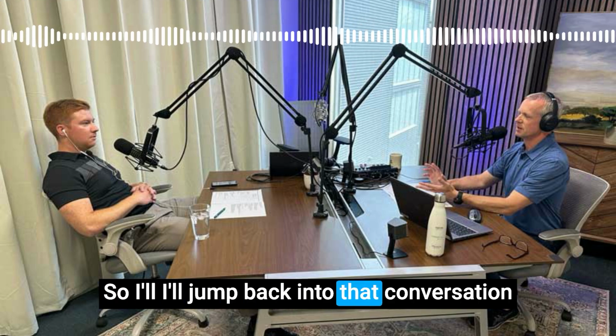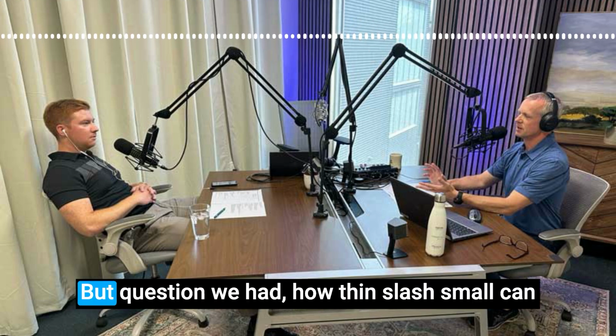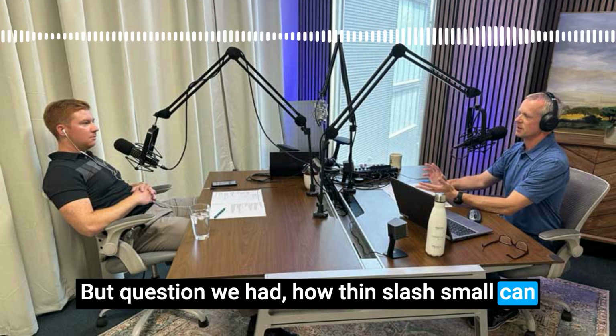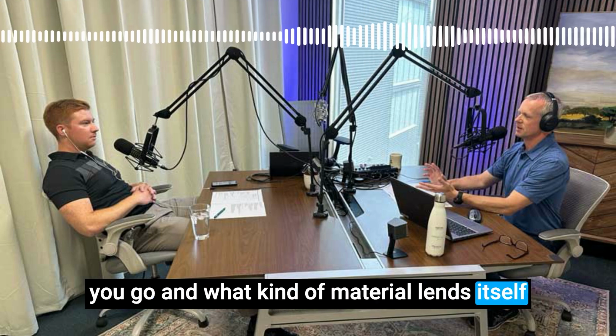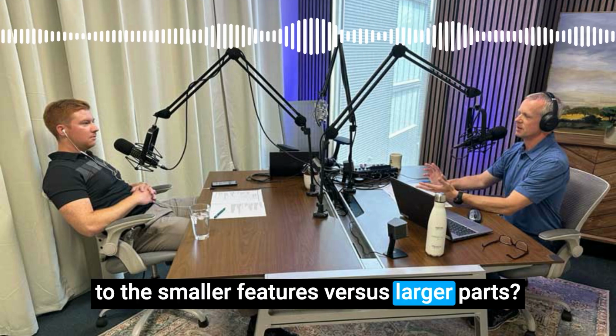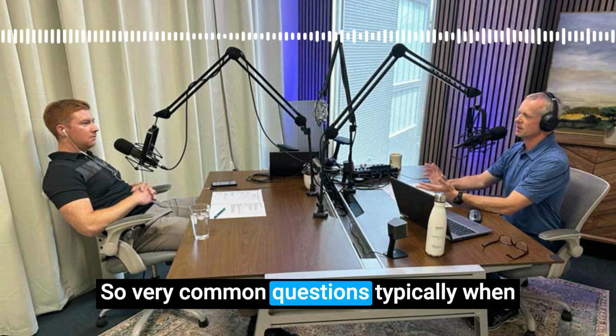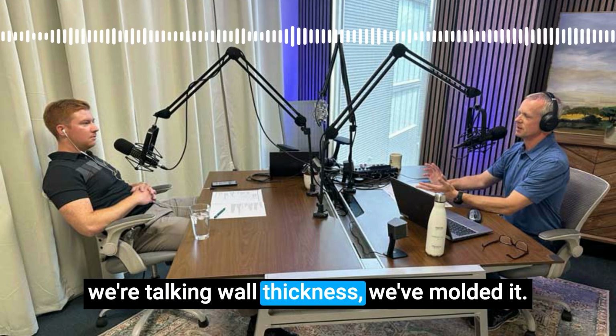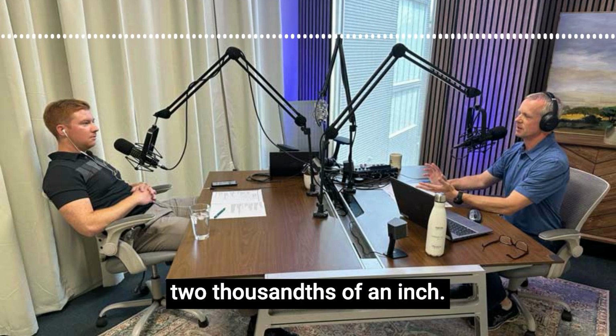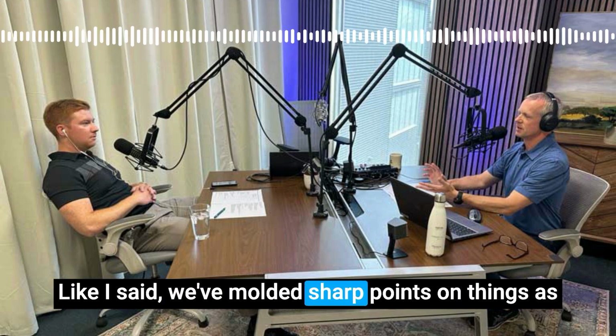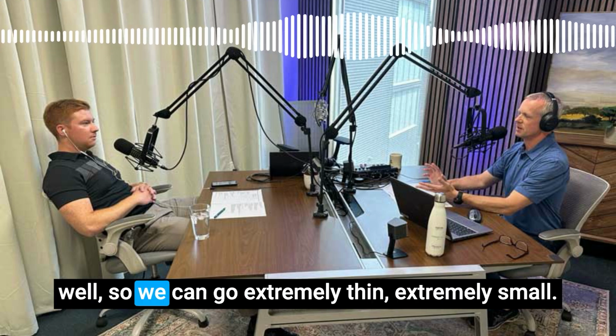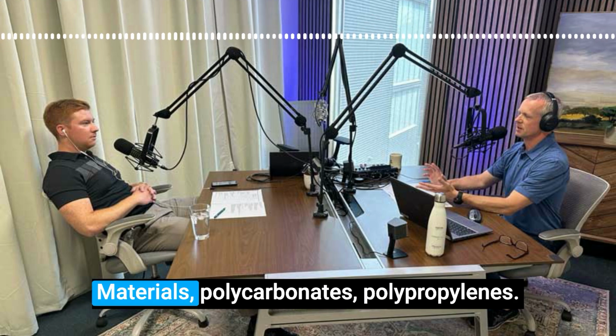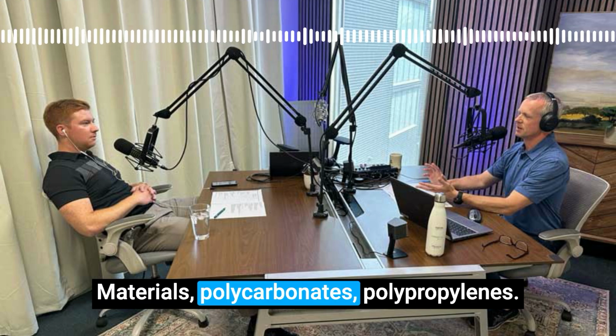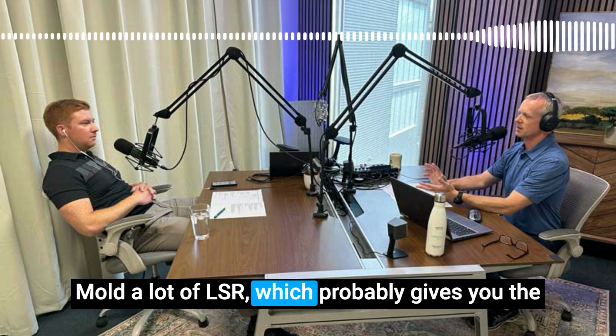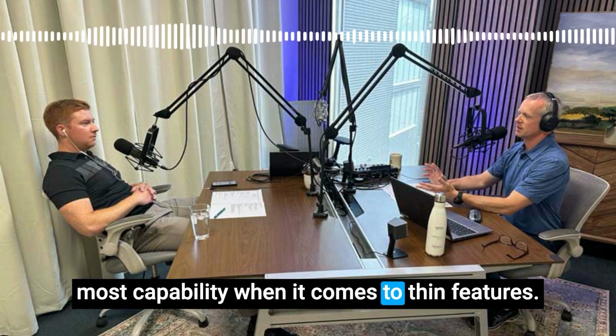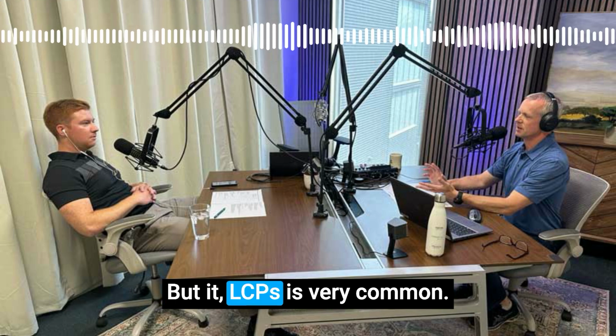So I'll jump back into that conversation there, Jeff, in a second here. But the question we had: how thin and small can you go, and what kind of material lends itself to the smaller features versus larger parts? So very, very common questions. Typically when we're talking wall thickness, we've molded wall thicknesses down to just 0.02 of an inch. Like I said, we've molded sharp points on things as well. So we can go extremely thin, extremely small. Materials: polycarbonates, polypropylene, we mold a lot of LSR, which probably gives you the most capability when it comes to thin features. But LCPs are very common.